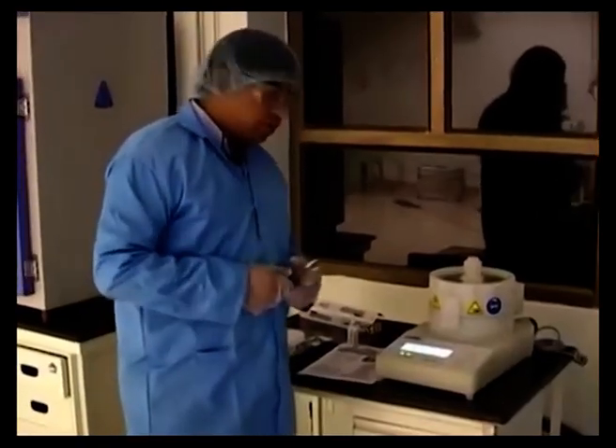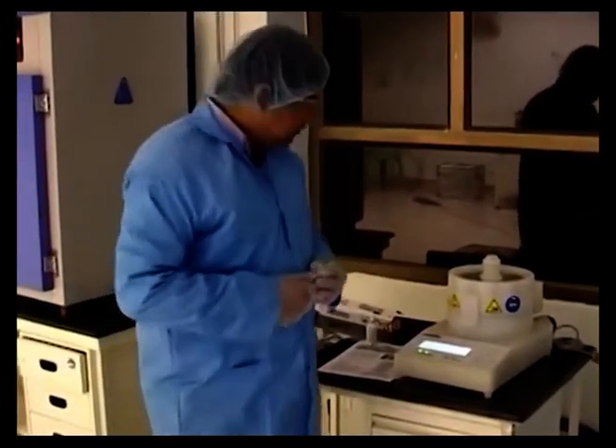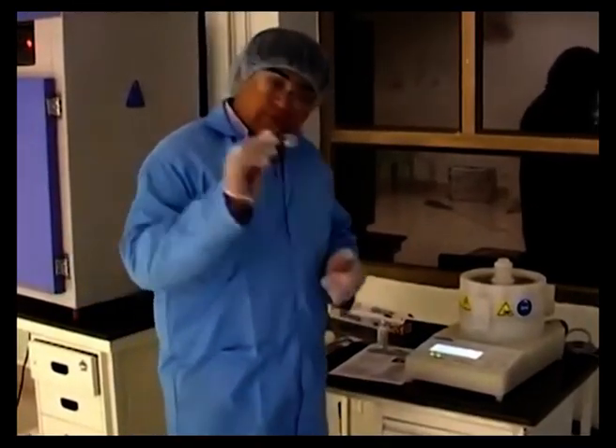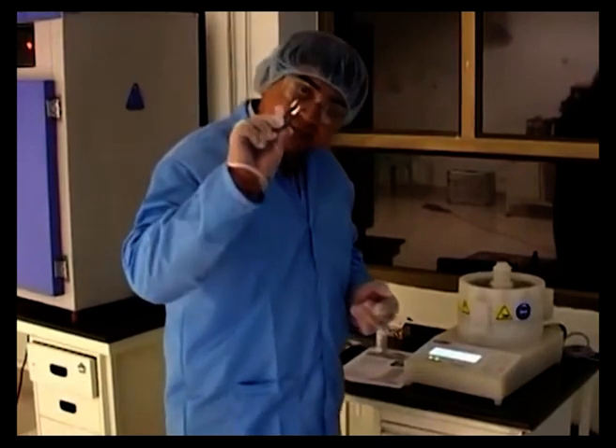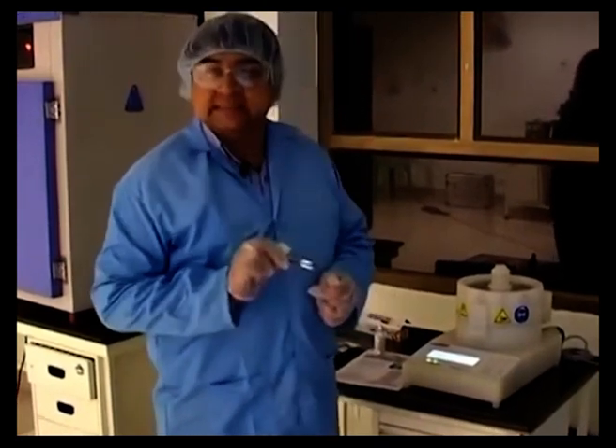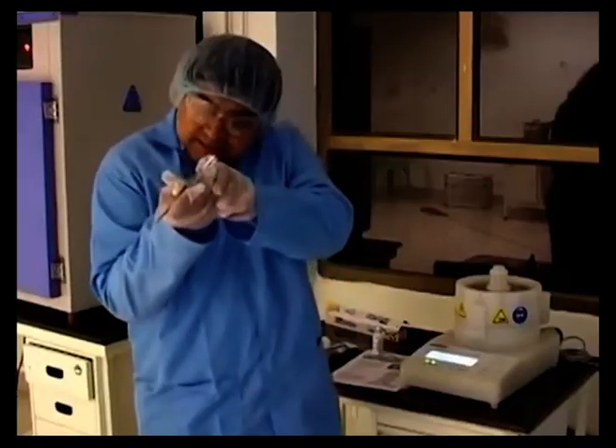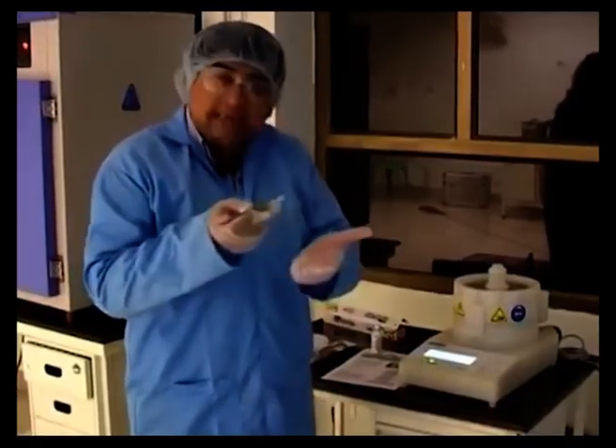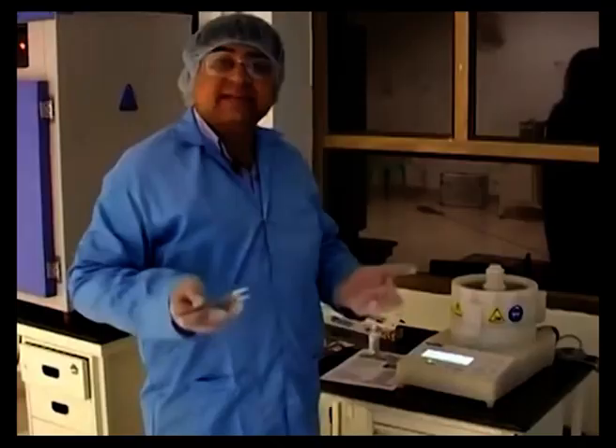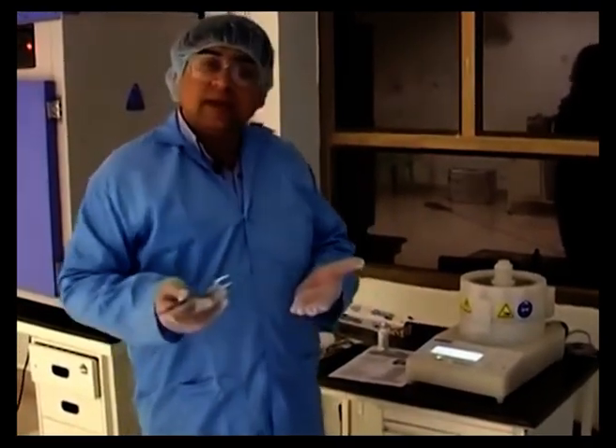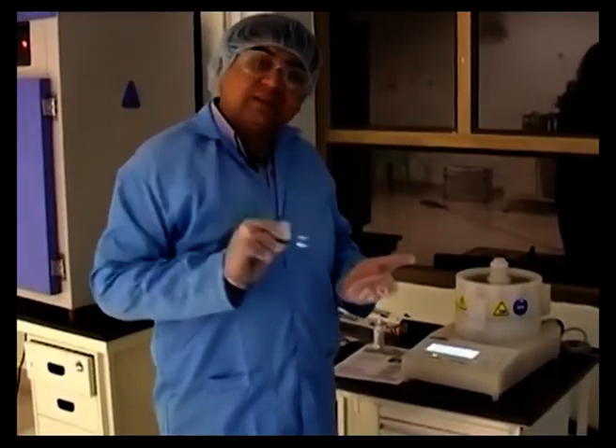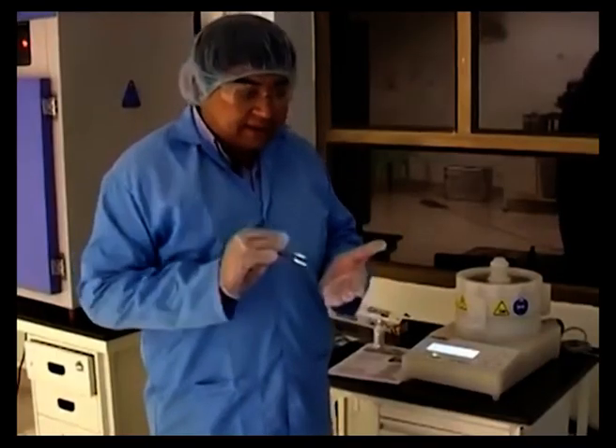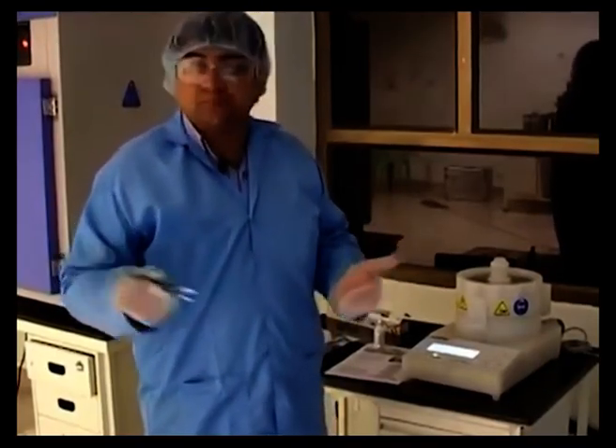So now the resist is actually spin coated, and we have to be very careful about removing the wafer. We have to hold it from a thin corner at the sides, because that is typically the area where there should not be any designs and structures. We'll just use a little bit of tweezer space for holding it and be extremely careful about handling, because mind you, at this stage the resist is a kind of liquid in nature. We have not cured it, and before the curing the film is tacky, and if you have any stresses or any impact on the film, it's going to create a huge difference and make the film not behave properly.